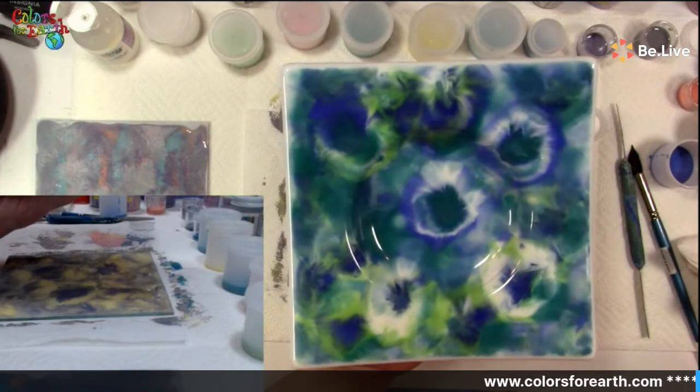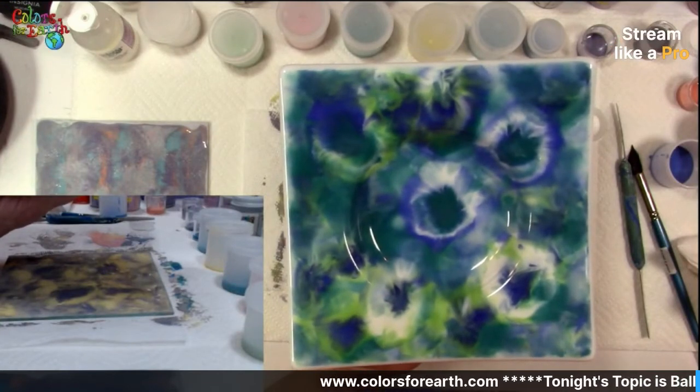So you can see if you want to cut it up, great jewelry. Let me switch back to my cameras since we're doing okay here. So yes, you could set the color at 1380, then come back and cap it with clear if you had just the sparkle and you didn't mix it with the color. That way it would become food safe. Now remember, copper sparkle does really well between glass. If you fire and set them, they do better, but they're a mica base, so they tend to mute out a little bit. Don't ever cap gold sparkle on the first firing or you will have flesh tone color. It doesn't work.